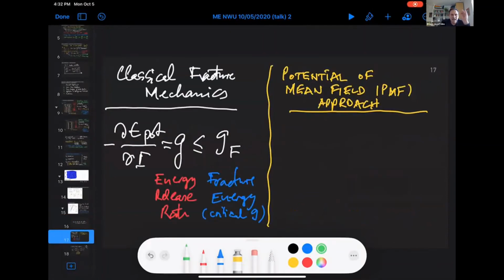So let's think about this from the classical fracture mechanics point of view. In classical fracture mechanics, you have basically the energy release rate, right? The energy release rate, the derivative of the potential energy with regard to the fracture surface, must be smaller than the critical value, which is the fracture energy. Now, let's make the analogy for the potential of mean field approach by noting that U, the energy, which I showed initially in my preliminaries, is the ground state energy plus, let's say, strain energy, U lambda, due to stretching.